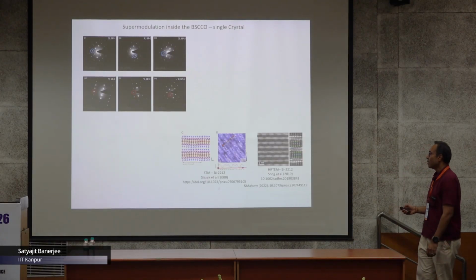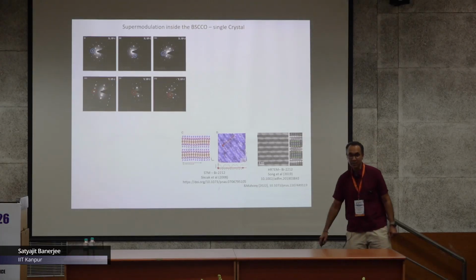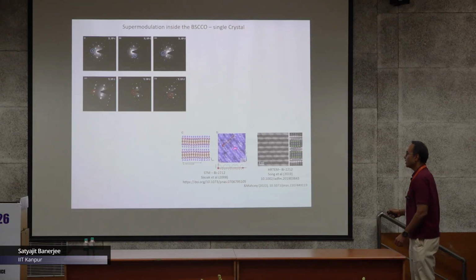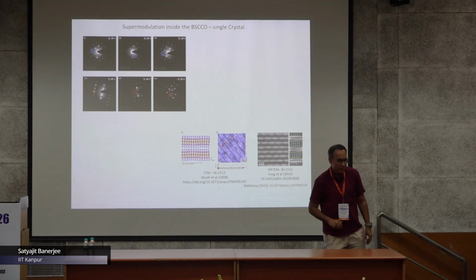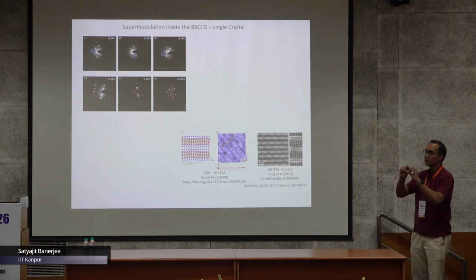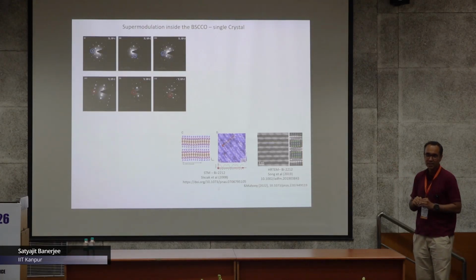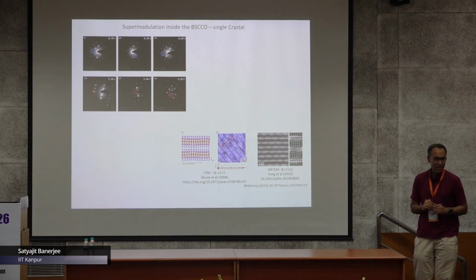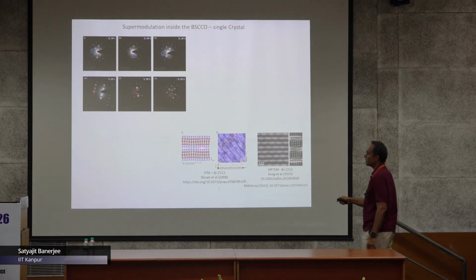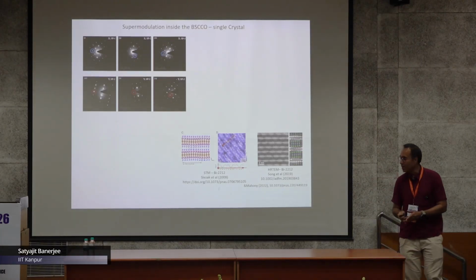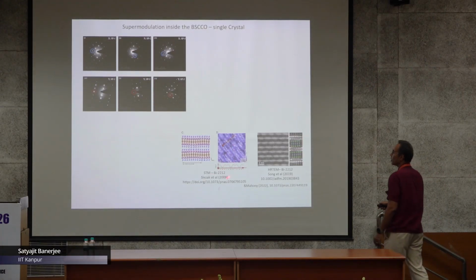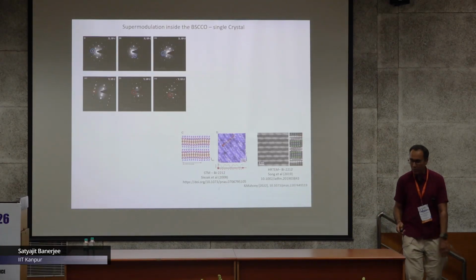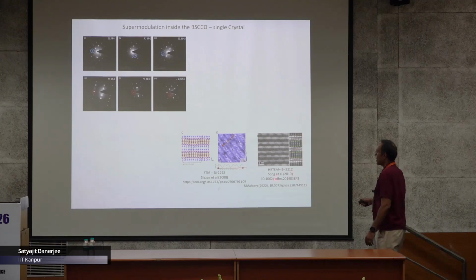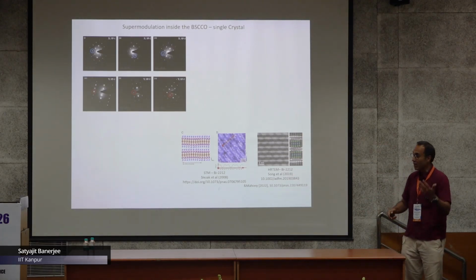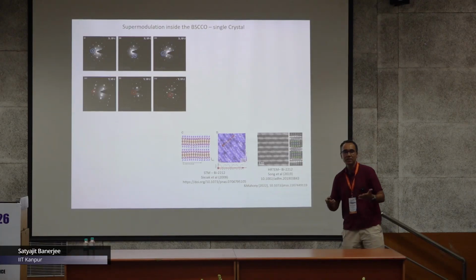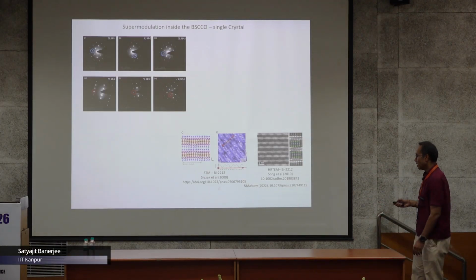It turns out people had seen similar modulations earlier in the 2212 BISCO phase, and this modulation is intrinsic to high temperature superconductors like BISCO, because you have this bismuth oxide, strontium oxide rock salt-like structure sitting on a perovskite structure. There is strain in the system, and this strain leads to a periodic modulation. But this modulation, reported in 2212 in 2008 and still being studied up to 2019, is on the length scale of a few tens of nanometers or so—we see something like 26, 27, or 28 nanometers inside the crystal.